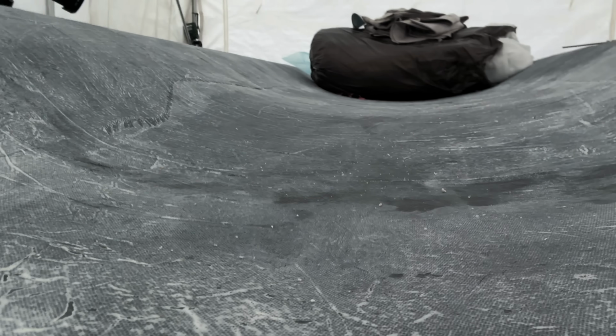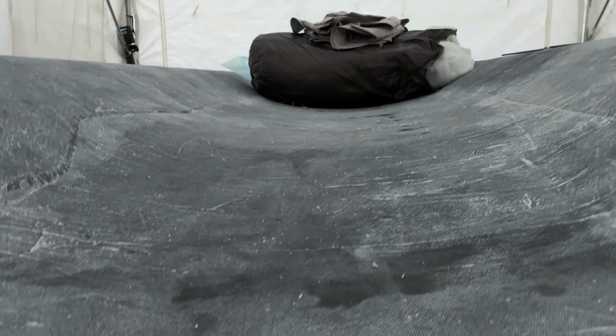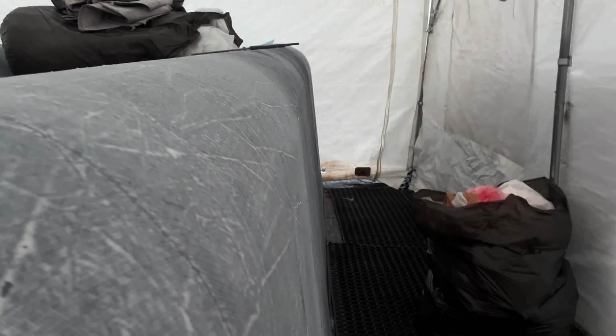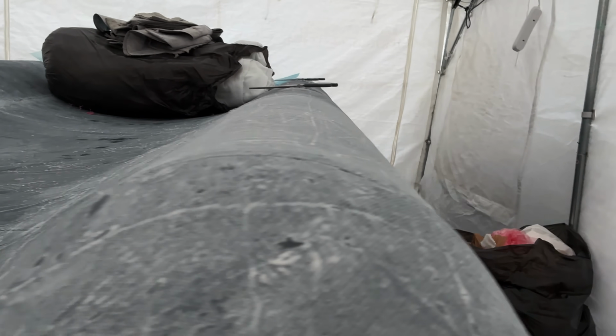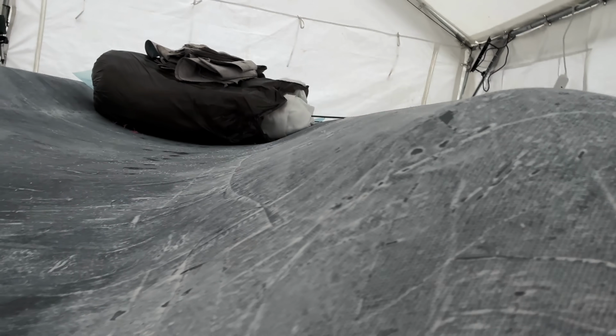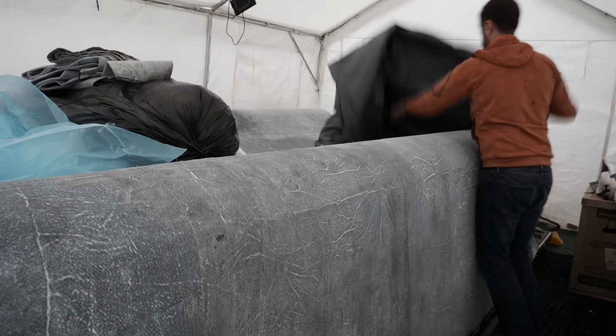First, I want to show you in a sequence of awfully panned camera movements the carbon fibre part. 1 ply thick only. The cure has been perfect. Thank you, Gurit. All the consumables worked a dream. Thank you, East Coast Fiberglass Supplies. But we only managed one structural ply, not the more than half a dozen that we really needed. Thought needs to be put in, and executive decision making. After I checked that the curves are being nicely conformed to, and after wrapping Bernard's mould up, safe from drips, dust or other nonsense. Bernard does now have a cover. In fact, it's a car cover for an extra large SUV.